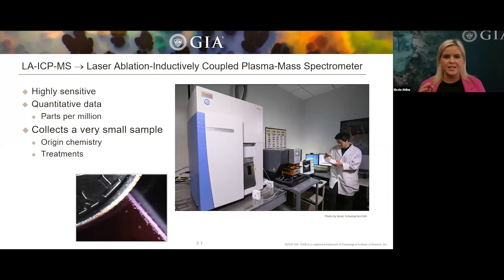Okay, so pictured here is our laser ablation inductively coupled plasma mass spectrometer, or ICP. And this device is highly sensitive and it collects quantitative data, and it's analyzing the chemical composition of the stones in parts per million. It's rather quick and direct examination of both loose and mounted gemstones, and it can do precise measurements of a wide range of elements and down to ultra trace amounts. And this device is helping the lab with treatment calls such as beryllium diffusion. It provides us data for all our geographic origin calls. It can also aid in a natural laboratory grown call as well for a wide range of stones.